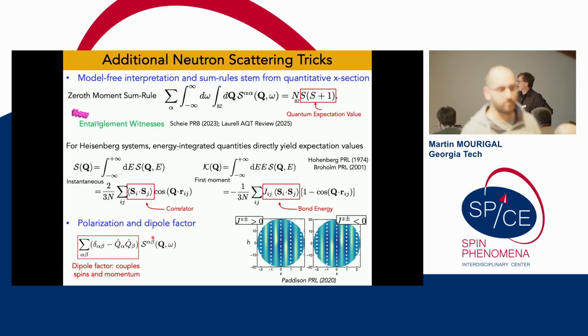Okay, good. So in the cross section, we don't directly measure the structure factor. We measure the projection of the structure factor perpendicular to Q, and that element in the cross section is very useful. Here's an example from Joe Pattison where you can show that this projection perpendicular to Q, if you have a system that is anisotropic in spin space, lets you understand directly, through this polarization factor, the type of anisotropy that you have without any true modeling. You can just sense how spin space is related to momentum space, and therefore you can know what type of spin anisotropy exists in your system.